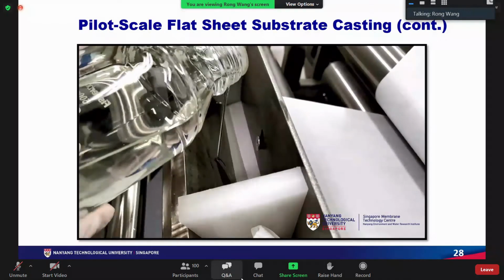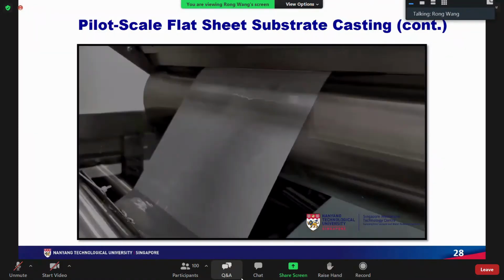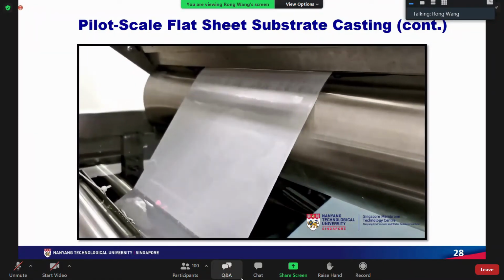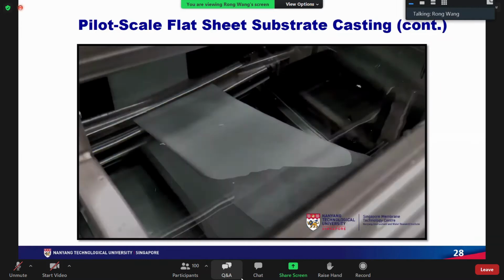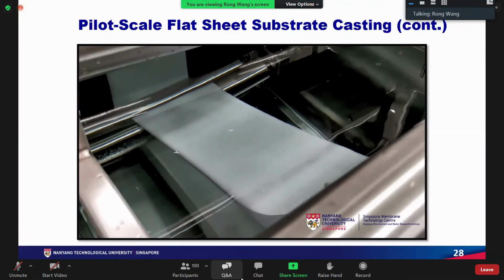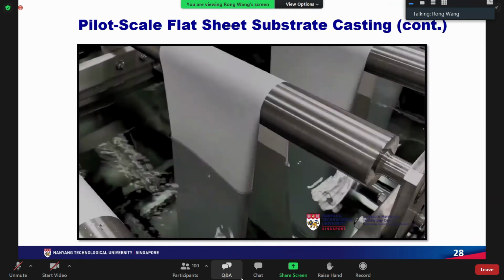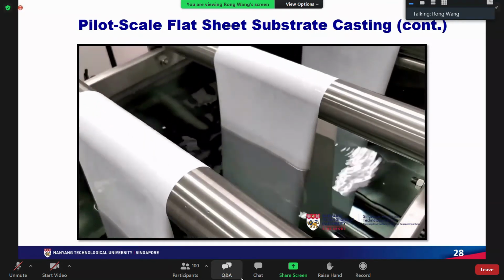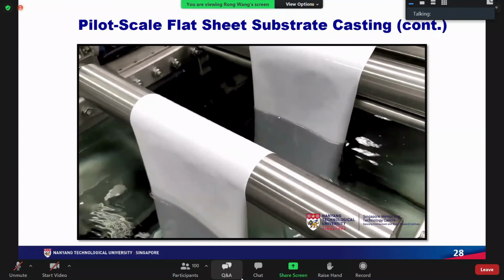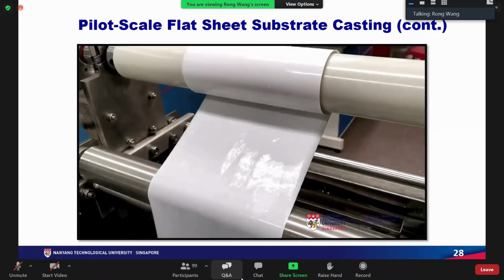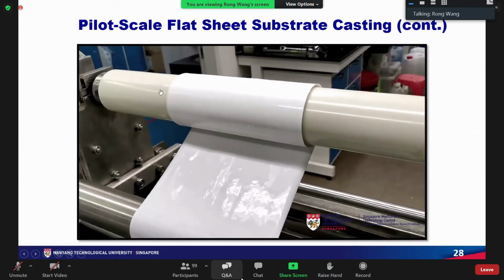You can see here, we prepare the polymer dope and we use the PET non-woven as a support. After the polymer film is applied on the support, it enters the water bath and precipitates, and we can form the UF type membranes as a substrate. The width of these membranes is 60 centimeter. Through these machines, we found the substrate performance is very good. It has very good quality control. The reproducibility is very good.